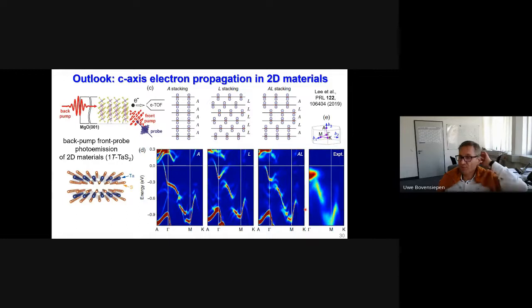And one very brief outlook is that we currently work on bringing this toolbox to two-dimensional materials. So basically, we let these electrons propagate in two-dimensional materials. One example is tantalum disulfide, where there's a discussion going on, highlighted here, that the stacking should really influence the propagation along the c-axis of this material.